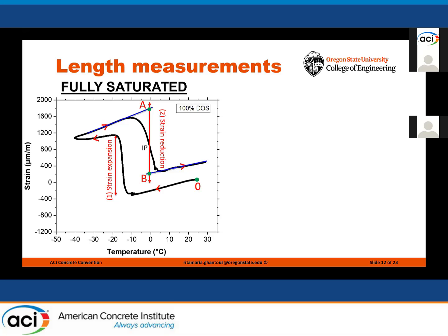Then the temperature is increased again to room temperature, and the difference between the initial length of the sample at 20 C and its final length at 20 C allows determining what we call residual strain, which is an indicator of freezing and thawing damage. Then we compare the values obtained from residual strain with the damage index obtained from UPV to be confident in the values we get from length change measurements.